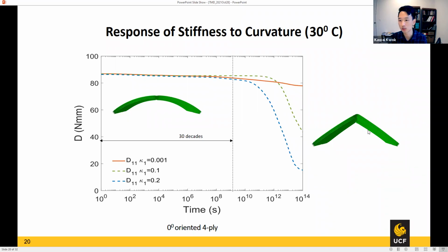And we see that there is localization of deformation that does not happen at the beginning, but only happens sometime afterwards, and that's because you have matrix that is concentrated in the region where the matrix is the richest. So you have the plain weave, and in some region, this crossover region, the matrix is the richest, right? So there's proportionally more matrix than the other parts of the structure. And then you get more relaxation there. Over time, all the energy wants to go there because that's easiest to deform, and that is setting up a localization scenario. And then finally, we thought this might be the reason that precedes failure, because now you accumulate a lot of strain here and it's going to break here.